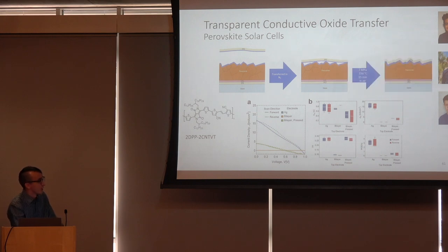And so we went ahead and heat pressed those same devices under 2 megapascals, 150C for 15 minutes in air. And well, the resulting devices still are not performing as well as our controls, but see a significant improvement in charge extraction in our short circuit current. And well, they're actually producing power now. And so, you know, there's optimization left to be done. It would be really nice if we're not performing this pressing in air. We're going to be trying to get some chemical polishing agents and just generally try and improve the smoothness of our perovskite films. We think that after these optimizations, we'll be able to at least get these bilayer films to be comparable to our controls. But this is the current state of things.